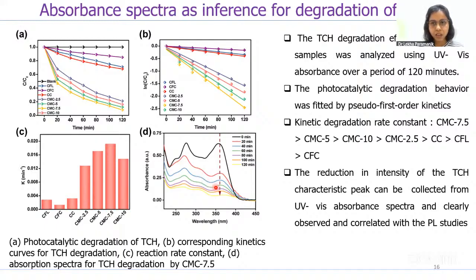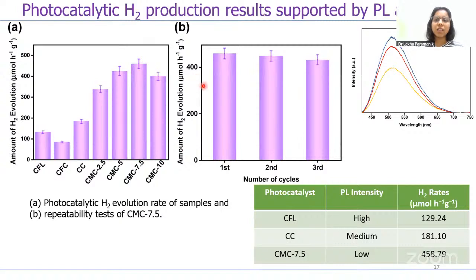by CMC 7.5. This is the result that I obtained from photocatalytic hydrogen production of all the samples, and the highest rate was obtained for CMC 7.5. This table correlates the activity with the PL intensity. The material with high PL intensity shows the low result.